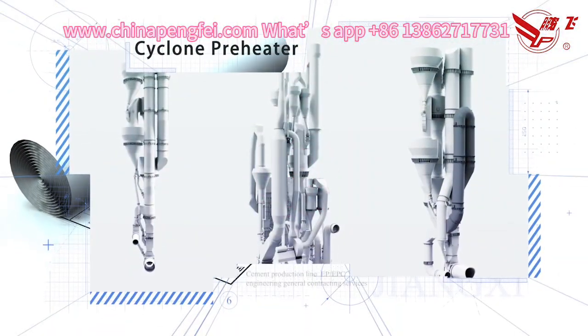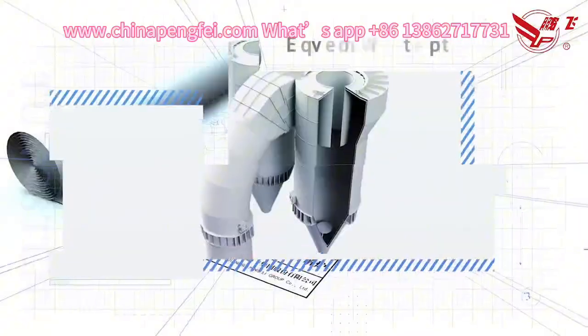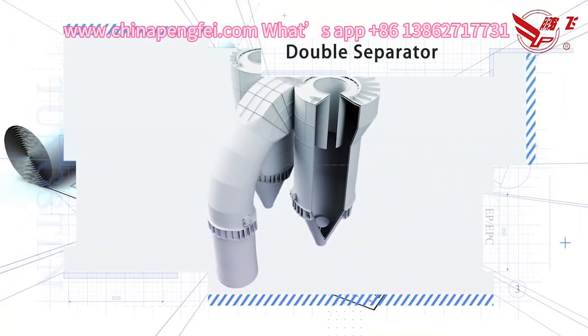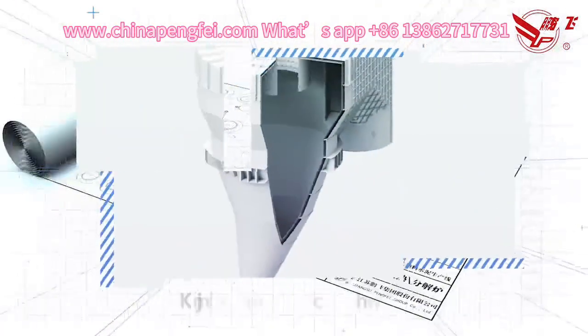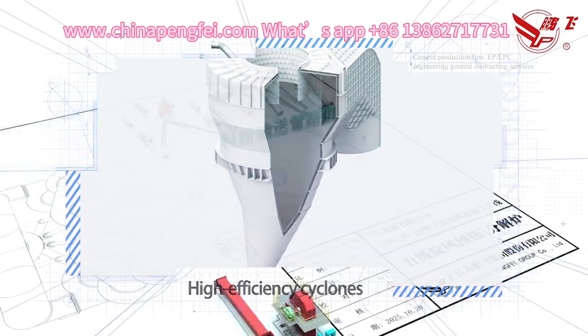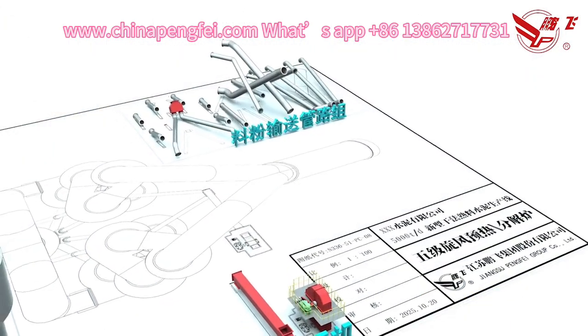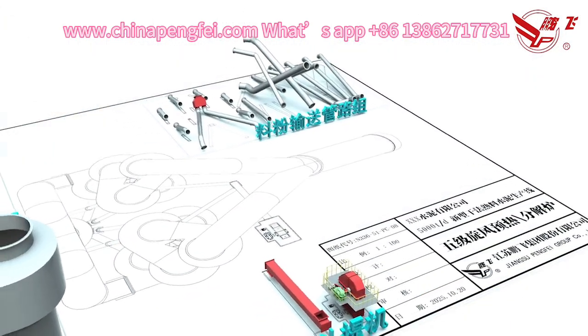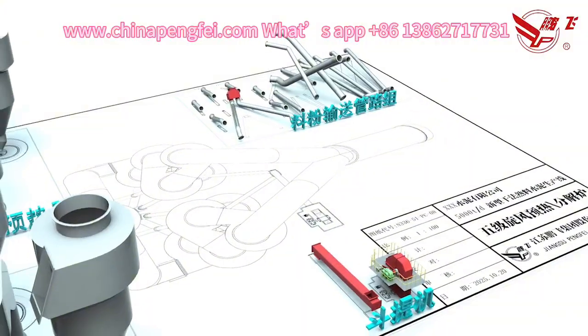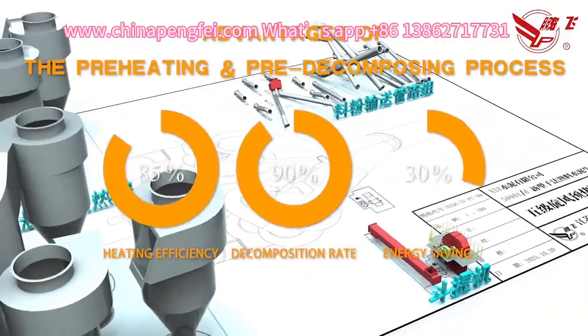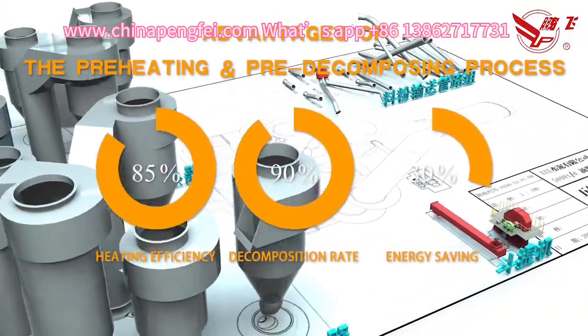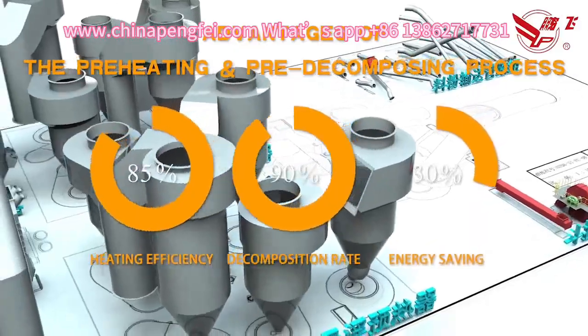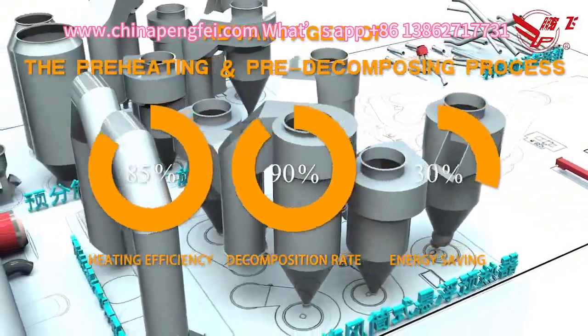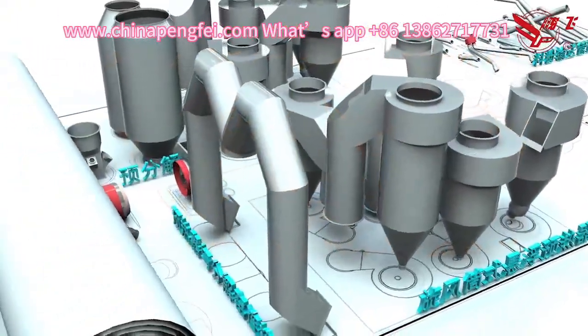The collaborative work of suspension preheater, pre-calciner, and rotary kiln can achieve efficient calcination of raw materials and full utilization of heat. The preheater and pre-calciner can increase the heating efficiency of raw materials by more than 85%, and the decomposition rate of calcium carbonate exceeds 90%, saving more than 30% energy compared to traditional processes.